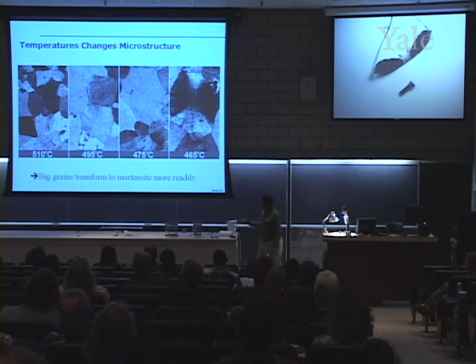So we see already that there's a significant difference in the way that you cook these materials or the way you anneal these materials. You get very different microstructures. At high temperatures, you have big grains, and they have quite a bit of martensite. At low temperatures, you have smaller grains and not as much martensite. So in terms of that process, relating the process to the microstructure, we've gotten that part done. The last part is to relate this to properties.